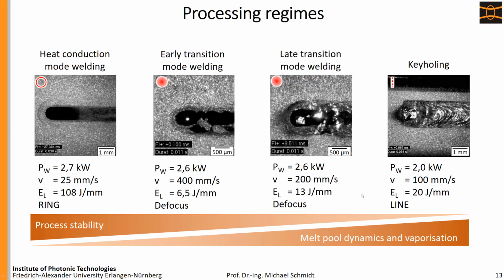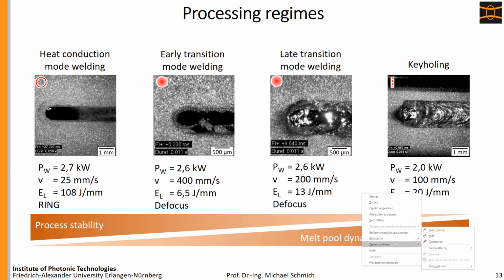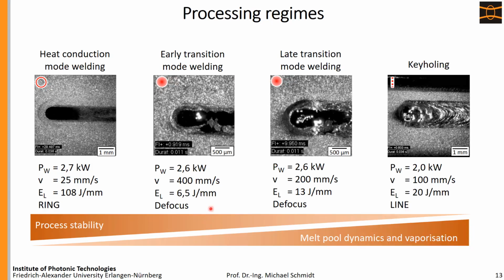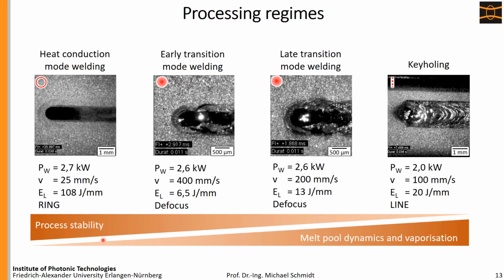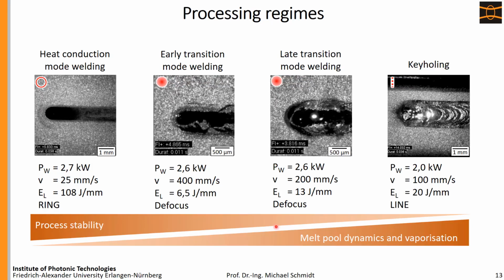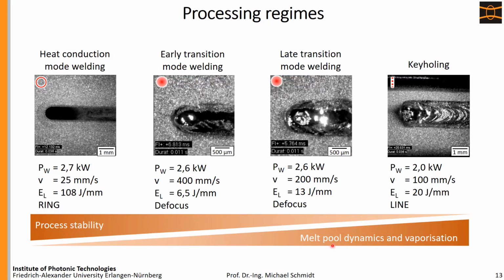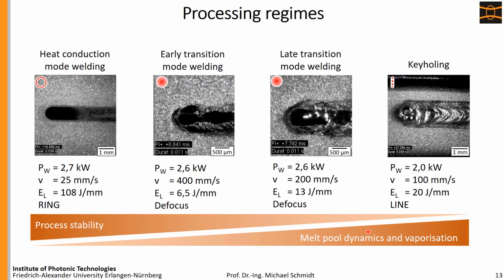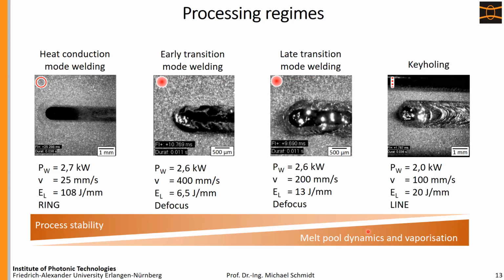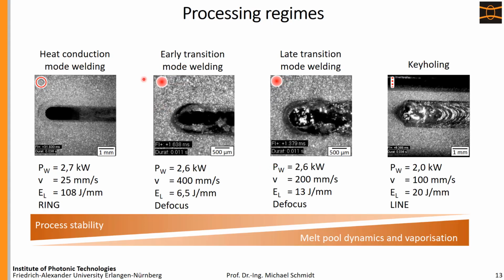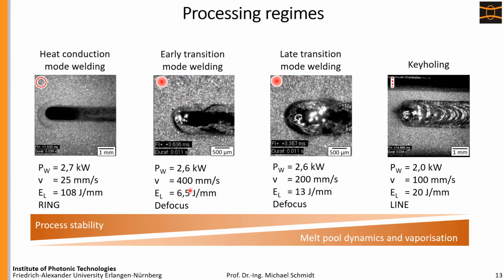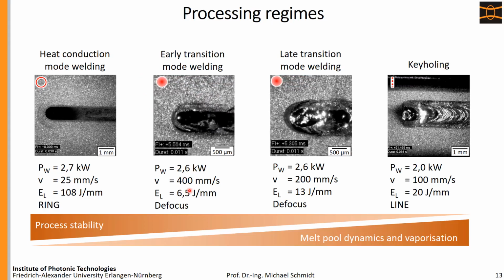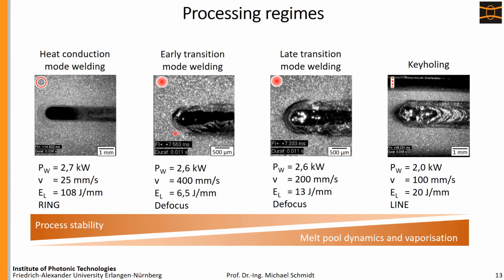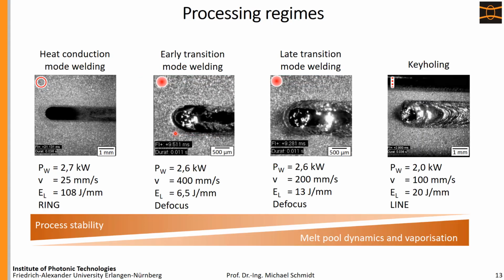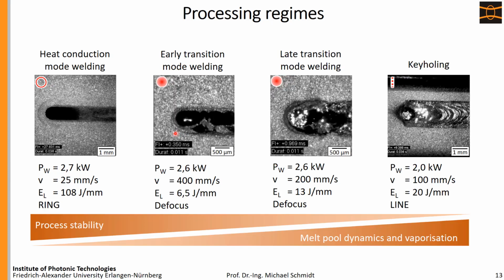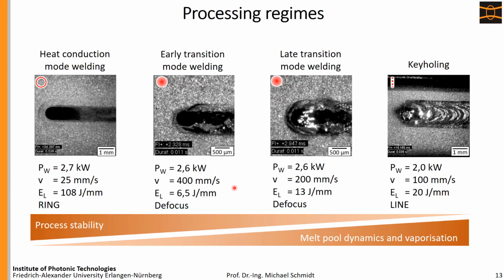So, in general, we can draw the conclusion that on this side we have the better process stability, whereas when we go to the right side, process stability decreases and melt pool dynamics and vaporization increase. Of course, we want to always be in between. It's easy to say, okay, then we use a defocus and have just less line energy, and then we are not in the transition mode but remain in the heat conduction mode, but then we are slow. And productivity is one of the main things that needs to be increased in additive manufacturing.